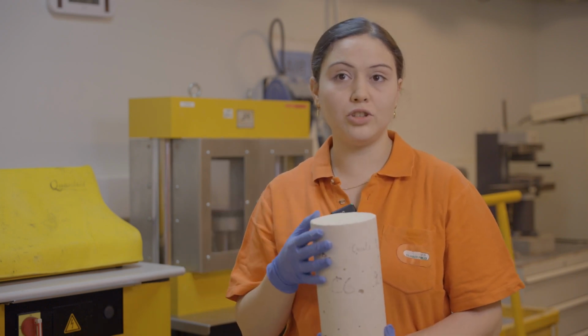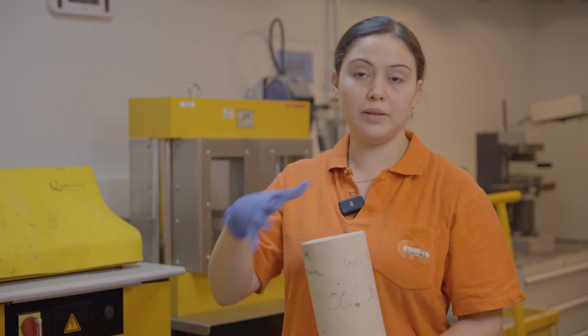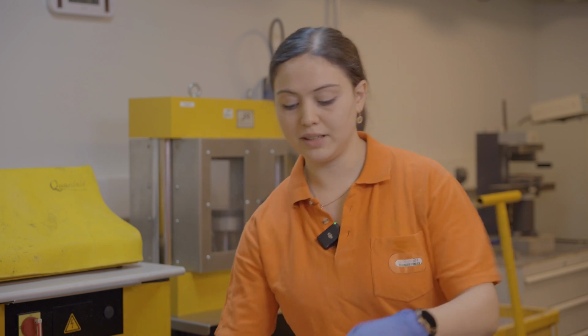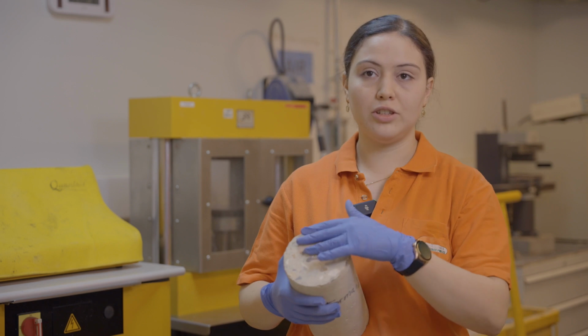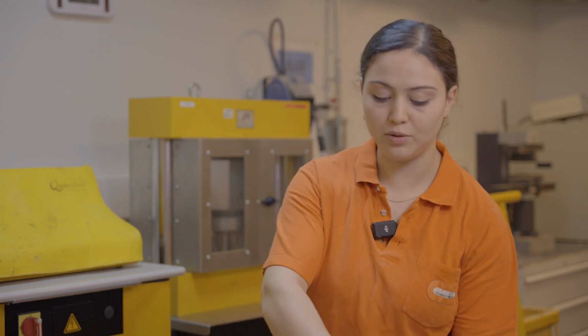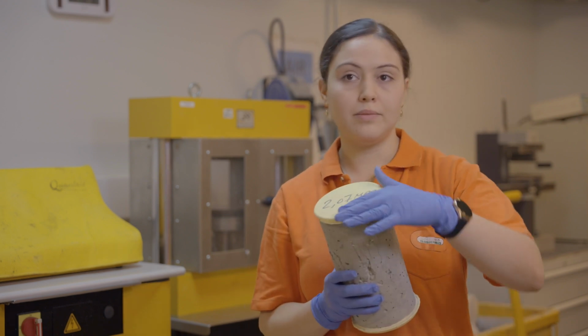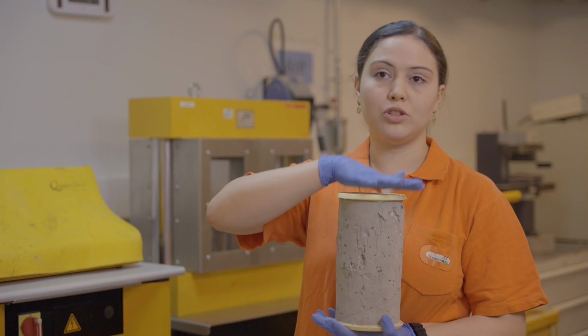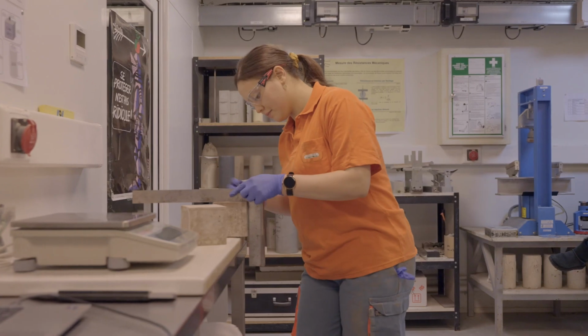In this case, we will check the condition of the specimen. If it is strong enough, we can proceed directly to grinding to obtain a smooth surface. But if the specimen is not as solid and shows signs of crumbling, we have to perform sulfur capping. And again, this is to have two smooth surfaces, ensuring an even load on both sides.